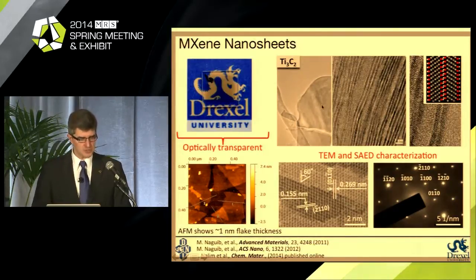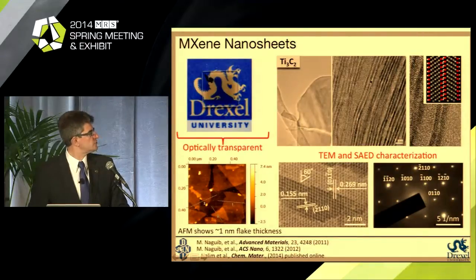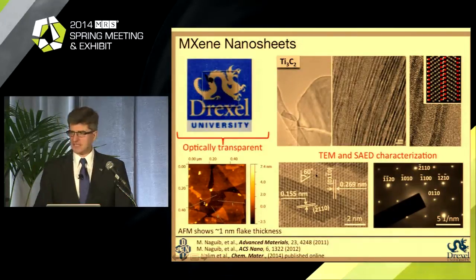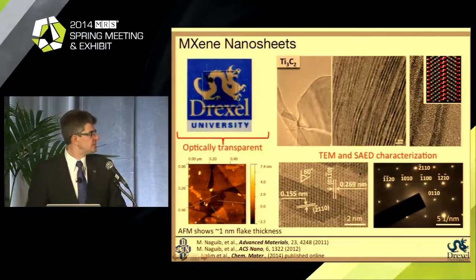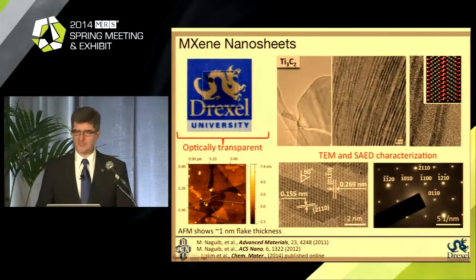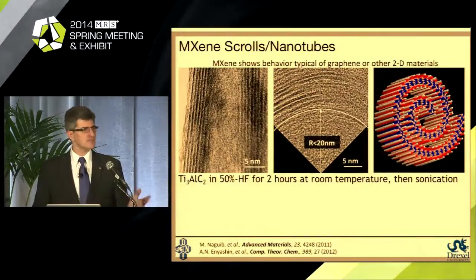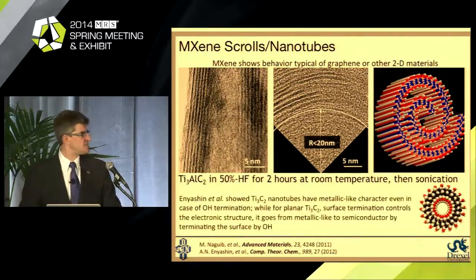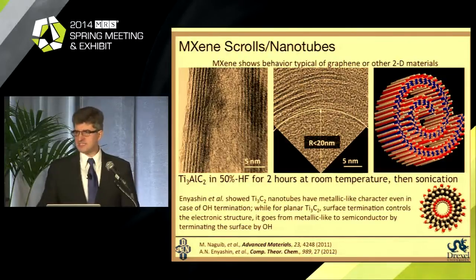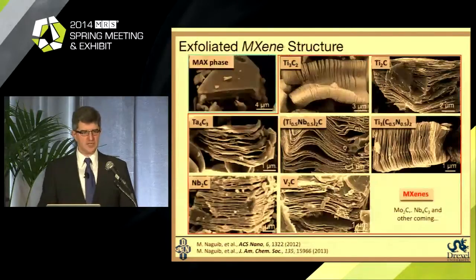of MXene structure, titanium carbide Ti3C2. You can see in transmission electron microscopy that you can get single layers, which are separated, as well as multilayer or double layer, triple layer MXene. They maintain their crystalline lattice ordering in the film, as you can see also from high resolution TEM and electron diffraction. Like other thin layers, they can roll into scrolls just like graphene, and it has also been predicted theoretically that seamless nanotubes can exist. They have not been made yet, but they're possible.